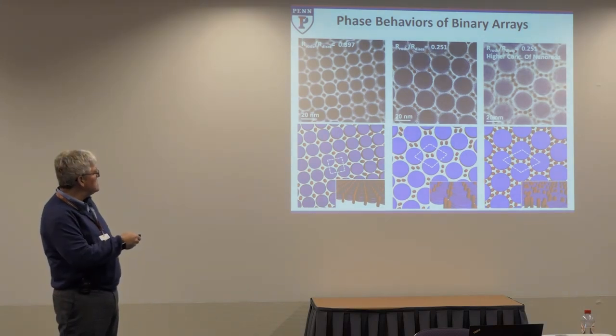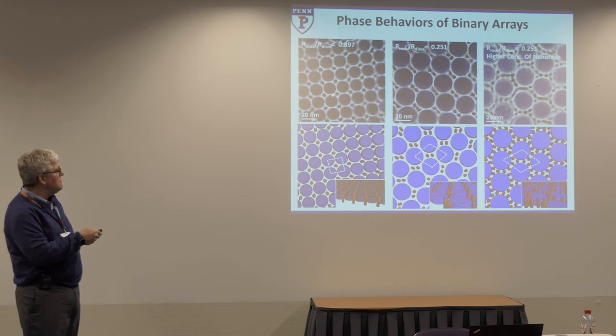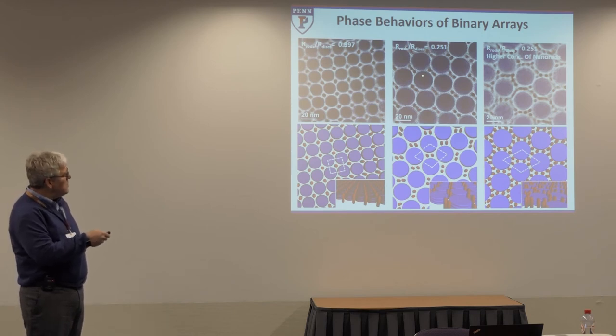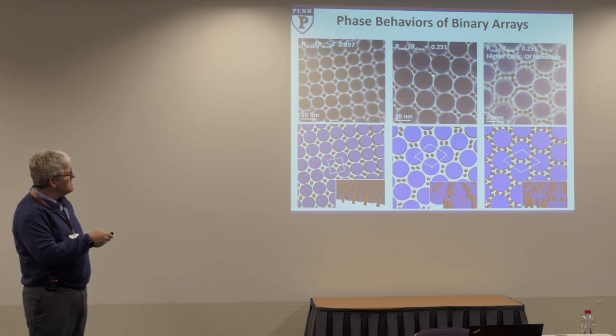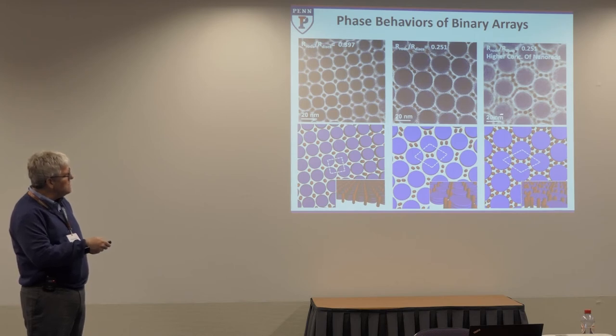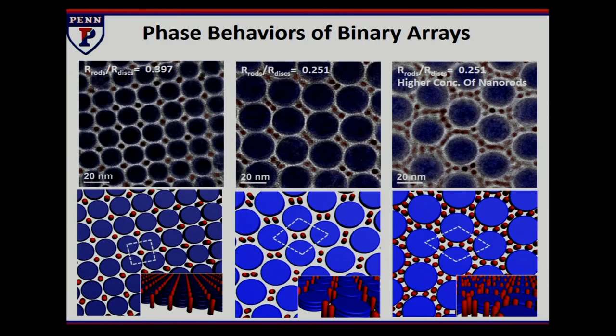So here's the single component system. You take slightly larger rods. Now two don't fit. Only one can get in between these guys. Or you adjust the system so that two rods can just fit to fill the available space. Or if you use really small rods, now you have that analogy to the earlier rod sphere example where the disks pack in a crystalline array, and the rods now have enough free volume that they're more like a liquid phase. They're kind of disordered all through the structure. But they're orientationally controlled. Right? All the rods are still pointing in the opposite direction to the disks in the system.